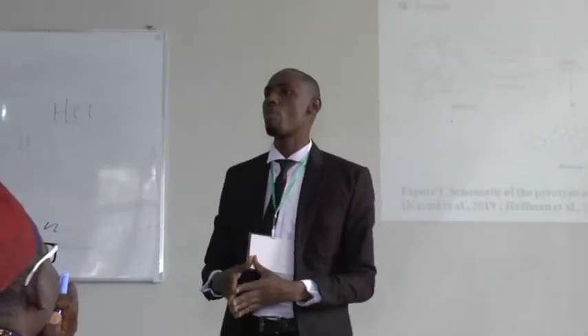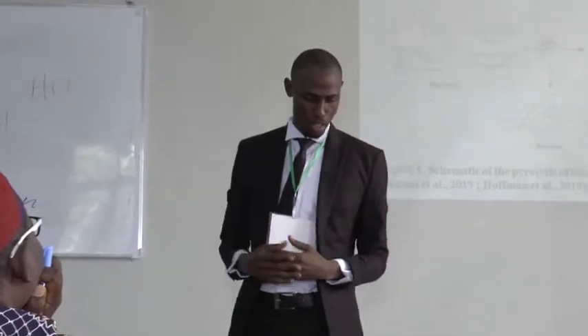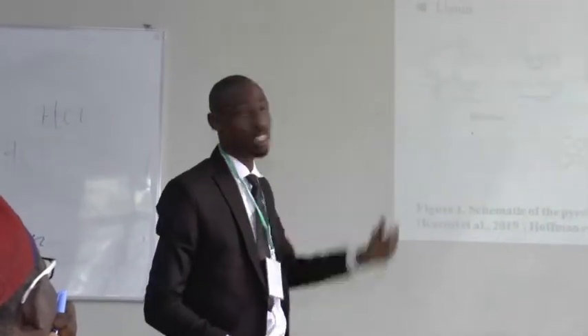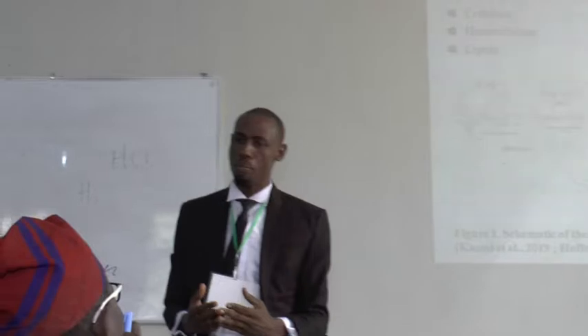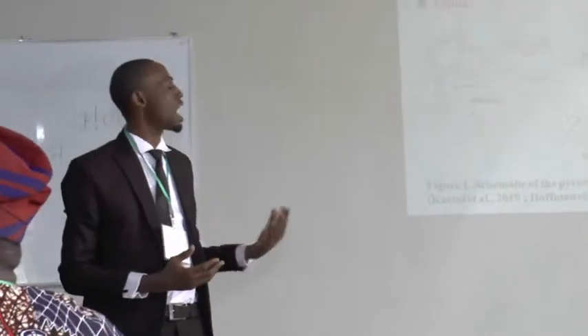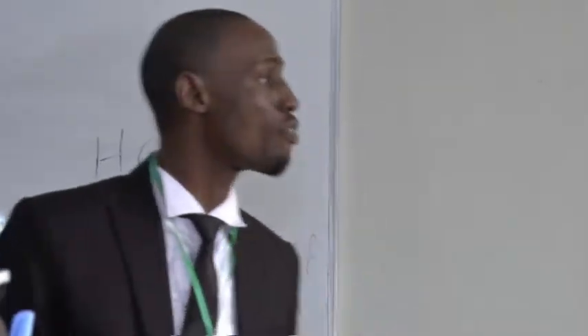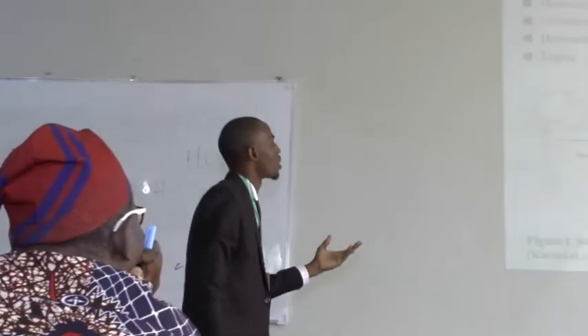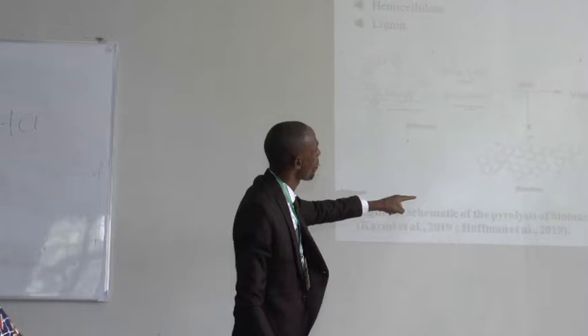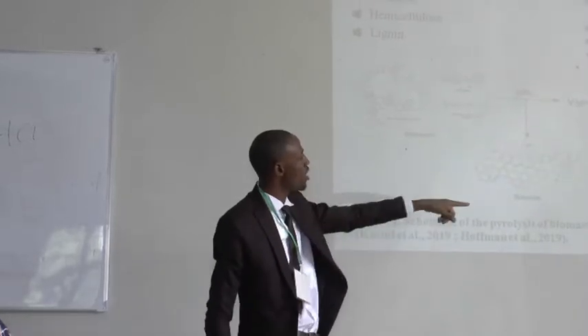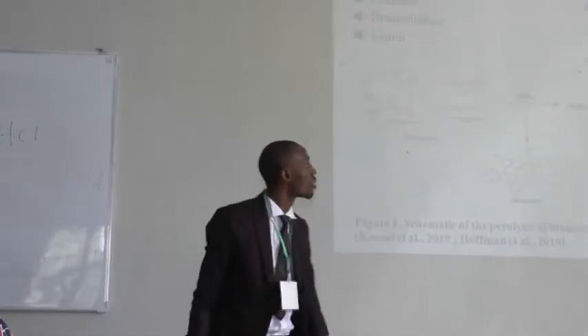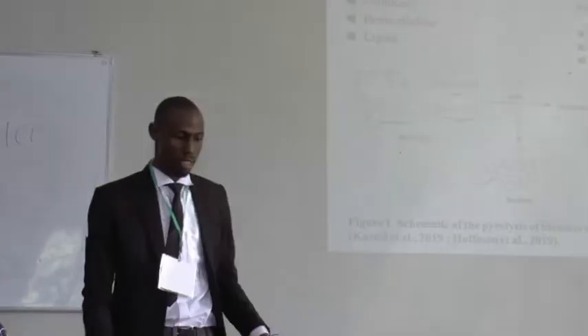Pyrolysis is the thermal decomposition of biomass in the absence of oxygen, while co-pyrolysis is the thermal decomposition of more than two biomass in the absence of oxygen. Biomass is mainly composed of cellulose, lignin, and hemicellulose. The decomposition of this composition of biomass leads to the following products: the biochar from the lignin, the bio-oil from the cellulose, and the biogas from the hemicellulose. Next slide.